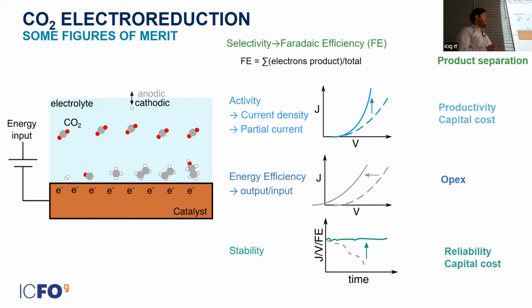Selectivity is very important because you want to be very selective towards a given product. Otherwise, separation costs when you scale these systems are huge and in some cases too high to be realistic. The activity of this reaction, that means how many molecules per second you generate, is one of the most important aspects too. In electrochemistry, this translates to current density. Considering the selectivity or Faradaic efficiency, the product of current density and Faradaic efficiency is partial current density. The partial current density towards a given product tells you about the productivity. So you want to have a very high partial current density towards the product of interest, for example, ethylene. This impacts the productivity and the capital cost of your system.